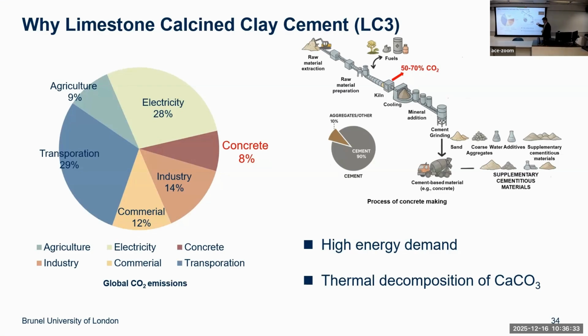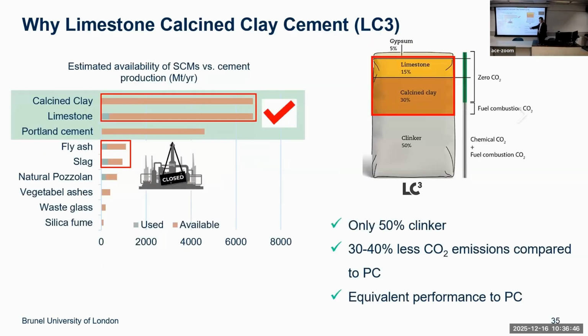Remember, at the beginning of my presentation the slide showed the journey to zero carbon concrete. One way is to try to reduce the clinker. So we are thinking of reducing clinker to 50%. We need clinker because it generates early age strength very quickly, and that's a beautiful property for concrete. So after one day you can strike the mold and move on to the next layer, the other stories. Now, Portland cement has 95% clinker, and now it's only 50%. So we're going to replace this 45% with 30% calcined clay and 15% limestone.